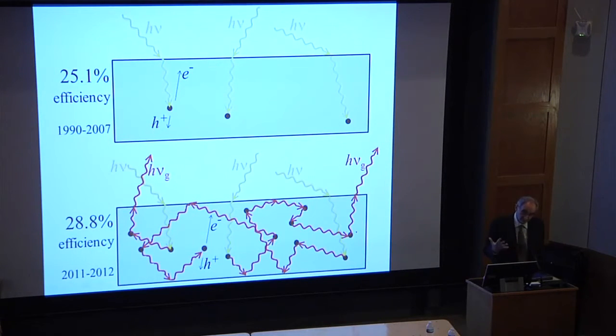Now, why is that? Well, if this solar cell is sitting on a substrate, and this material is epitaxial gallium arsenide, the best semiconductor you can have, but it's sitting on a kind of ordinary, unimpressive substrate. So any light that goes downward, 98% of light would go down into the substrate, and you'd never see it again. And as soon as you peeled the film, suddenly that sink for infrared light went away, and you could build up this internal photon gas. And so what happened in the company is they had a 96% reflector, and they broke the world record.